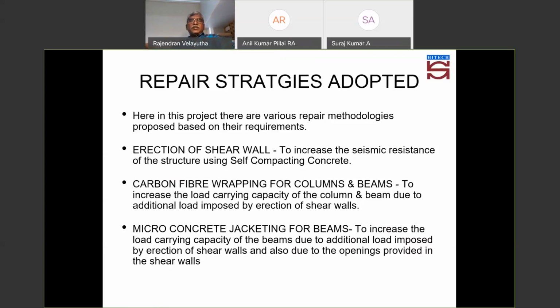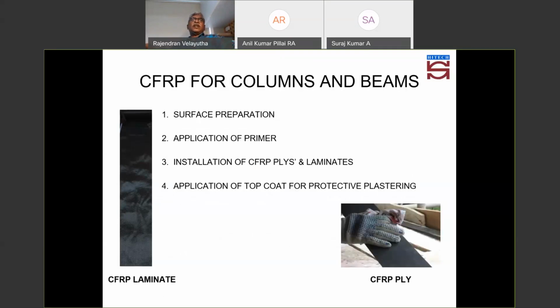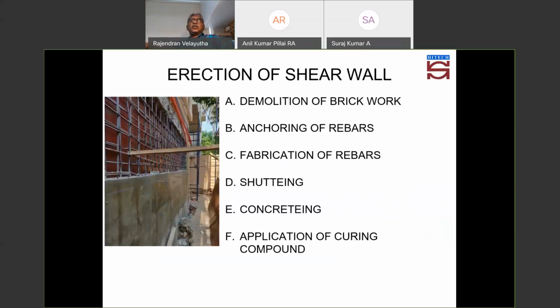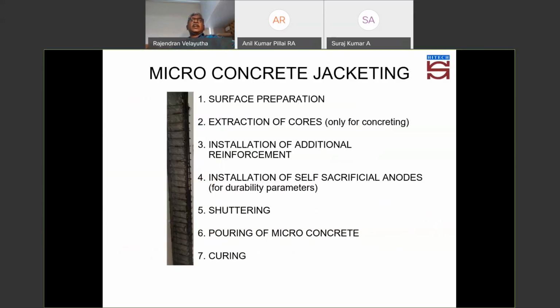So carbon fiber wrapping has been done for the columns, and jacketing has been done for the beams. A few beams are not failing on account of compression; they fail only because of flexure, so those have been done with carbon strip. So this is the system of how carbon is used, and this is the shear wall, how it has been done at that particular site.